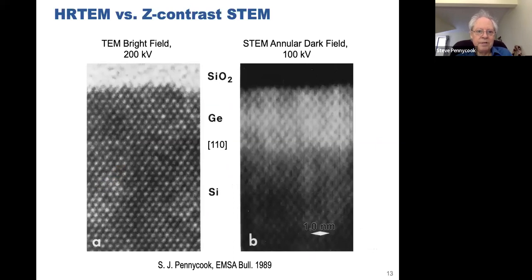We tried silicon. This is just a comparison of a regular TEM taken on a 200CX. Thin germanium film on silicon. And this, of course, is a structure image. So you don't get Z contrast when it's very thin. Only when it's thicker, you get absorption contrast. But on the STEM, annular dark field image here, very nice image of contrast between the germanium and the silicon. And you can see this interface very nicely. You can see this interface very nicely as well. No speckle pattern from the SiO2. Certainly looked like a nice incoherent Z contrast image.